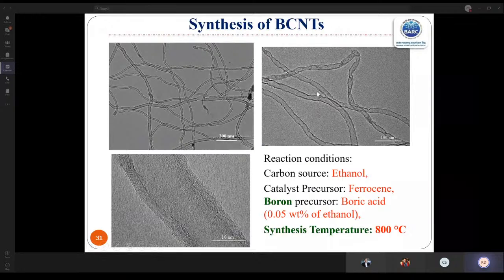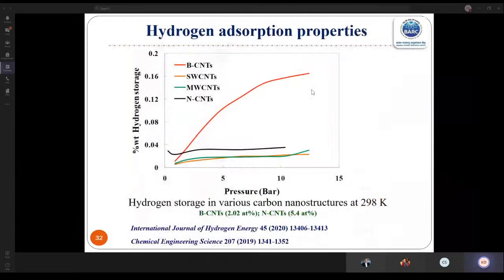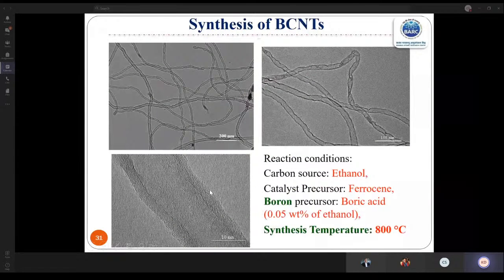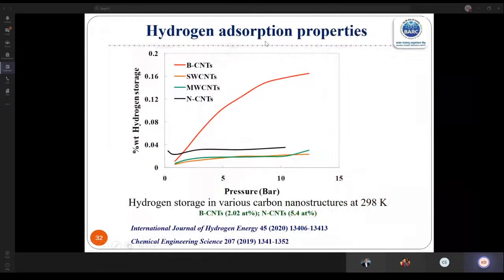Now, in case of nitrogen, you have seen there are bamboo-like structures, but when we dope boron, the structures are different. You cannot see that compartment type of structure now. Rather, you get almost hollow tubes, but there will be defects in the wall. If we see the hydrogen adsorption properties of boron doped, it is much higher. So if we see single wall carbon nanotube and multi-wall carbon nanotube, the hydrogen adsorption at this level, with nitrogen doping it has improved slightly, but with boron doping, it can really improve very high.